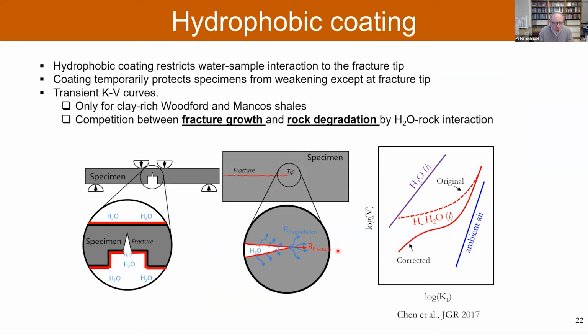The other thing we do is we coat the samples, especially the clay-rich samples, in a hydrophobic agent. That is to avoid the brine disintegrating the sample before we even test it. So the coating is applied over the sample, except for that induced seed fracture here. That's open to the fluid. So that limits the fluid interaction only to the fracture, which is more representative of the subsurface, because your fracture tip would be within a large layer of shale, and the brine would not necessarily get into the caprock from the underlying reservoir. So that's one way of making it more relevant to the subsurface conditions.